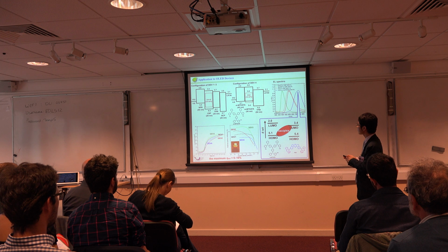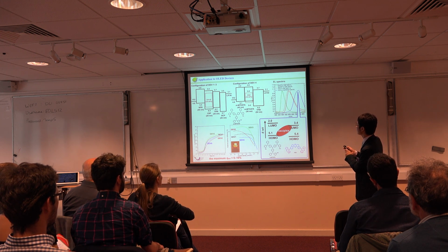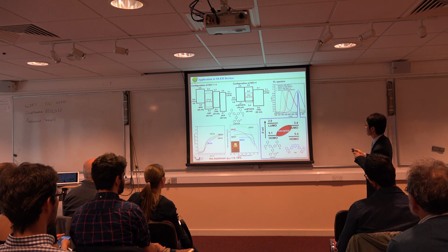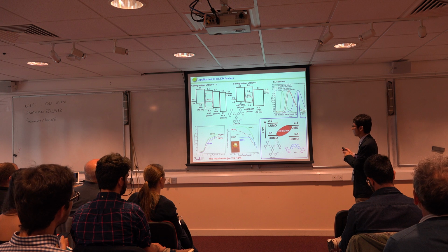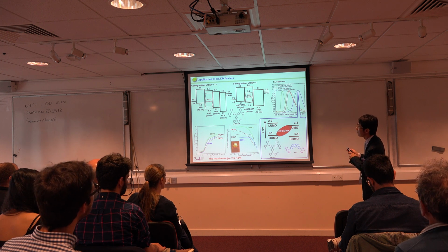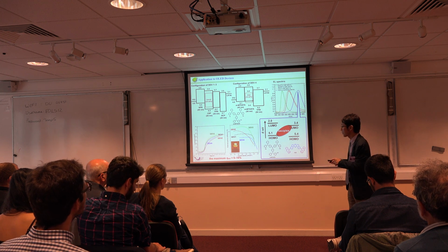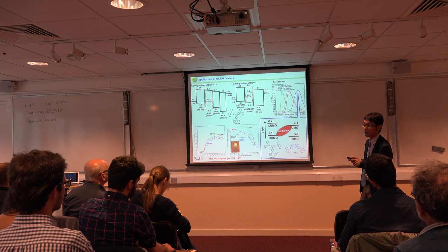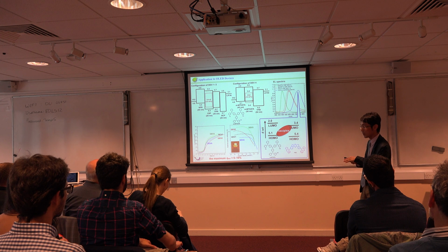Especially when you use an electron donor host material, effective exciplex formation was observed, showing light in the NIR region. This device showed about 5% external quantum efficiency, which is rather high for a TADF-based NIR OLED device.